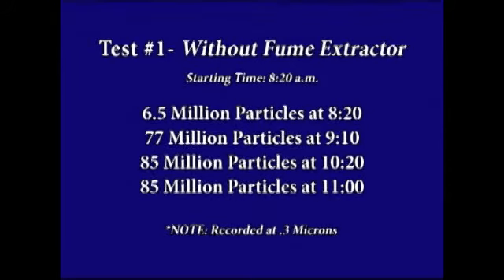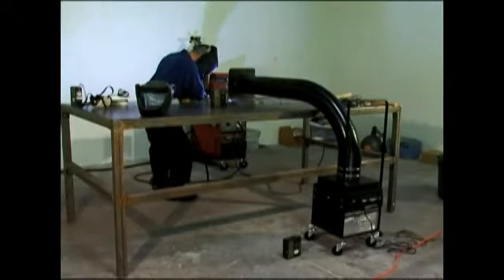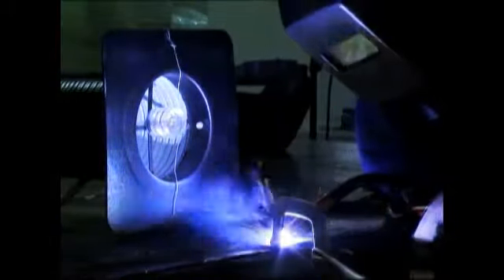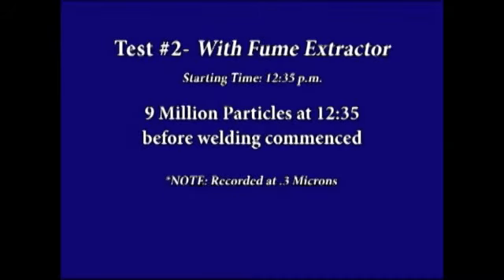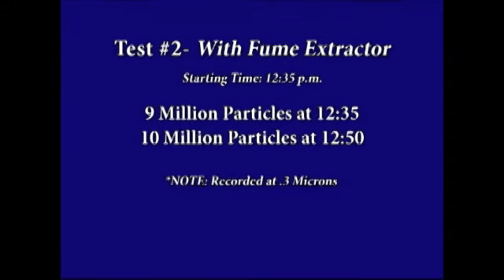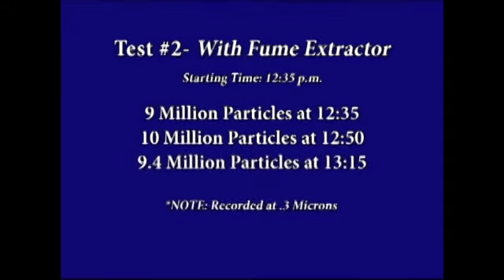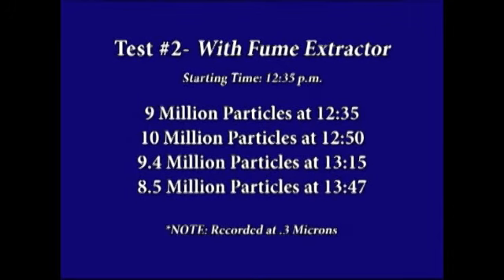In the afternoon, we returned to test the welding fume extractor with the same duration and identical conditions as the morning. The ambient count in the room prior to welding commencement at 12:35 p.m. was 9 million particles per cubic foot. By 1:47, the total amount of particulate had already dropped down to 8.5 million, which was lower than when welding began in the afternoon.